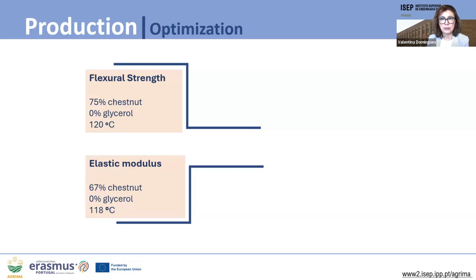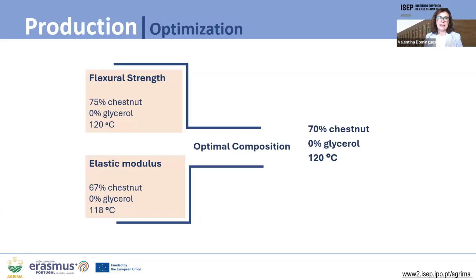For flexural strength, using the equation, the best is 75% of chestnut, 0 glycerol, and the molding temperature is 120. For elastic modulus it is 67% of chestnut without glycerol, and the molding temperature is 118. So considering these two properties, it was decided to use 70% of chestnut without glycerol and 120 of molding temperature.